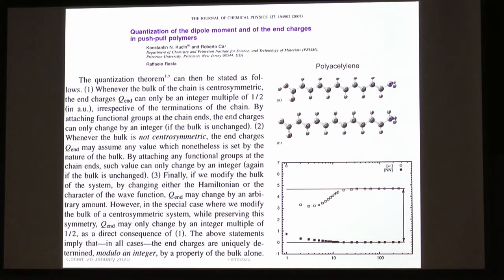So you don't really know the polarization of this system until you know the termination. So what you have beforehand, these two values here, I would like to call, instead of the formal polarization, the proto-polarization, because to me, formal polarization sounds like the real thing, and if the experimentalists don't get it, well, that's their problem. Whenever you're talking to experimentalists, you can translate it to their language. But I want to say that this polarization lattice is a potential set of polarizations depending on the termination of the crystal and the surface charge state. Only when you specify what the surface is, then you know what the polarization is.